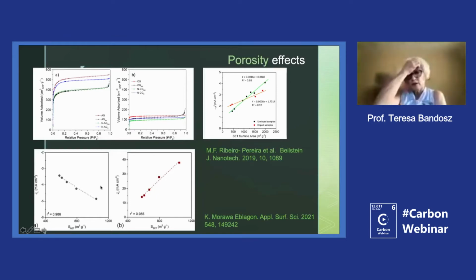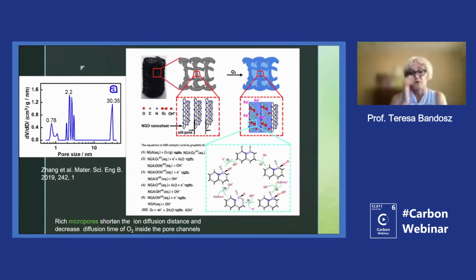And recently they also found a linear dependence of the current density on the surface area. And in this paper, for instance, the authors, Zhang and co-workers, used quite interesting carbons with a layered structure. And here is the distribution of the pore sizes. They stated that rich micropores shorten the ion diffusion distance and decrease diffusion time for oxygen inside the pore channels. However, how they do it was really not stated in detail.